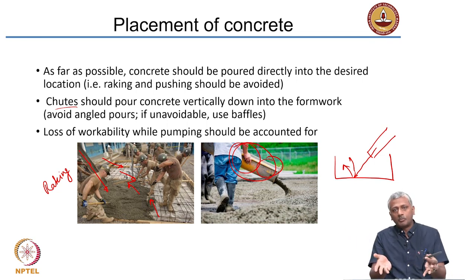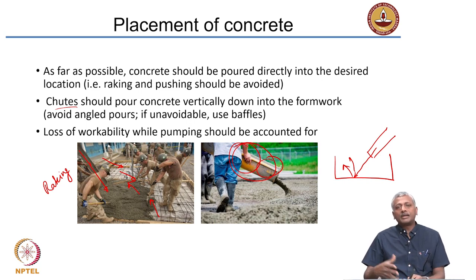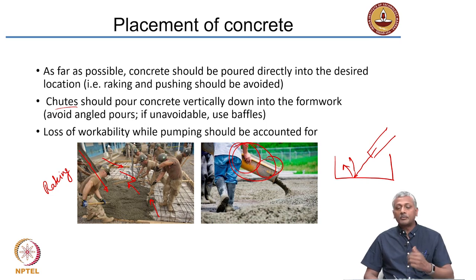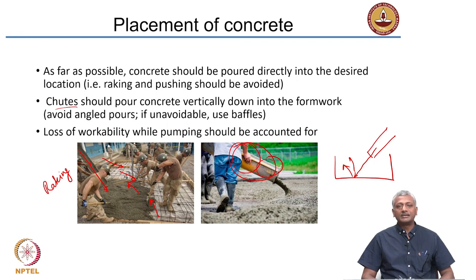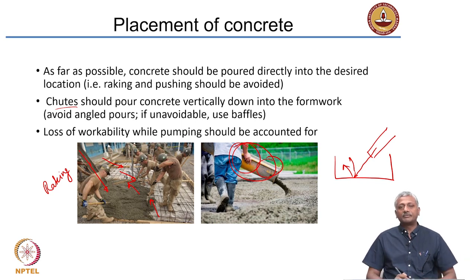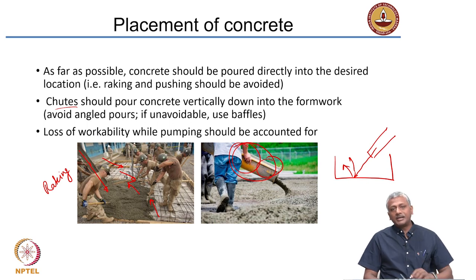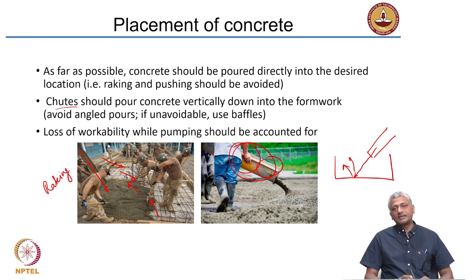For example, if you want a slump of 100 mm at the point of pouring, you need to design the concrete at the ground floor for nearly 150 mm to ensure any losses in slump during flow in the pipe are compensated. For Burj Khalifa, which is the tallest building in the world, concrete was pumped over a vertical distance of 600 meters — that is the world record for pumping concrete vertically. That concrete was designed to compact on its own, and maintaining workability at the 600-metre discharge point required careful planning and concrete design.